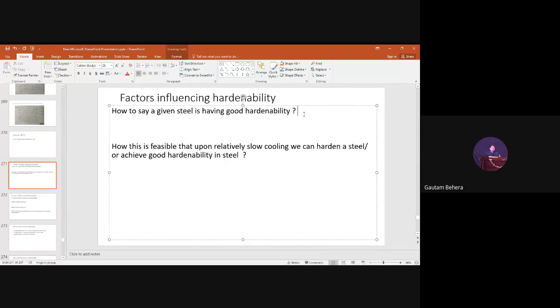So if you have a very high thickness of steel, the cooling rate will be different at different sections of the steel. In that condition, suppose you get 50% martensite and 50% pearlite at the center, that is also fine. Obviously at the surface you will have 100% martensite, but at the center if you have 50% martensite and 50% pearlite, that is also fine. You can say it is of good hardenability characteristics. But if the amount of martensite is below 50%, then I cannot say it is showing good hardenability characteristics.